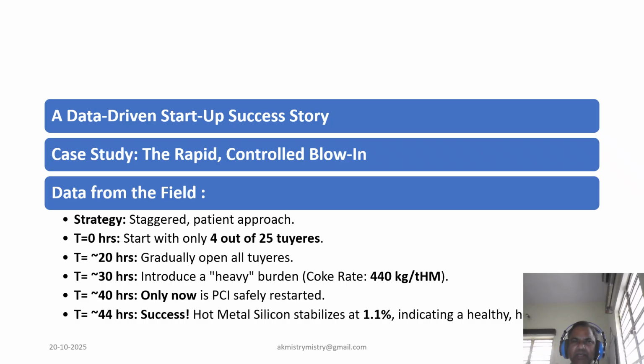to really drive the heat into the system. Critically, they waited until around 40 hours after startup before they safely restarted coal injection. No rushing. And the payoff: at about 44 hours, success. The hot metal silicon stabilizes at a healthy 1.1%. The furnace was hot. The process was stable. A textbook execution.